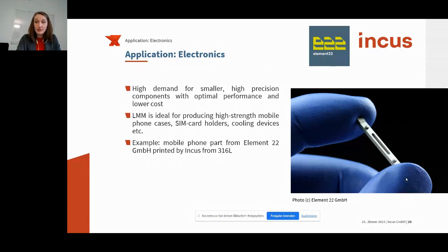And of course, the pictures that you see here are all as sintered, so no post-processing was done. There was no polishing. This is really the surface roughness of Ra of 2 micron. People are quite impressed every time we show that. And we also had a polishing company that said that it was so easy to polish our parts up to the point that we can see ourselves in the parts. So that was quite exciting to hear.